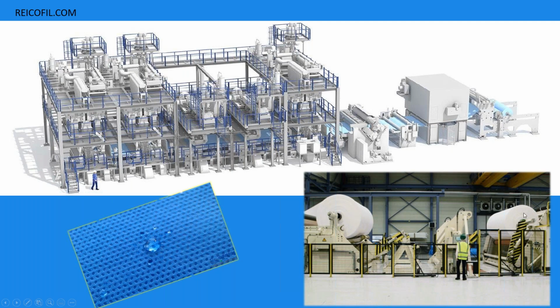And of course, you can see this picture here with the large rolls coming out. This is where they've made the roll, and then they're bringing it over here to unwind it and slit it into smaller rolls for the client so they can unwind it into their conversion process. This is the calender section. This is the section where they might be adding some fluorocarbon or other chemicals to modify its functionality and add some of that super hydrophobicity. Also, this is the curing oven right here, and it's an Omega style, which means it's a big drum. And of course, we've got a winder.